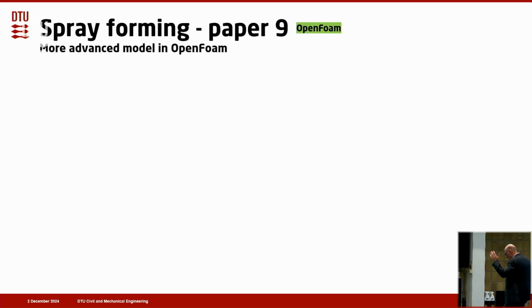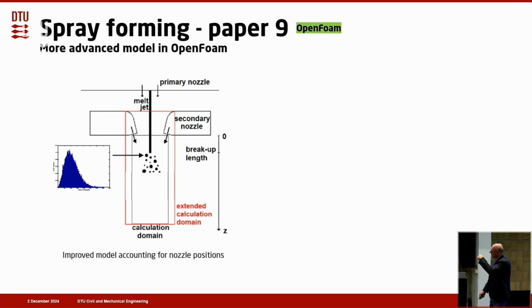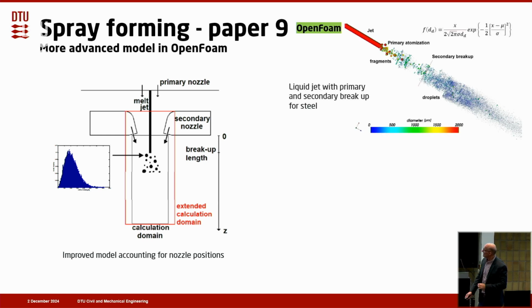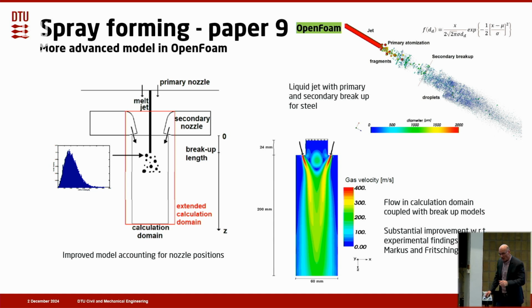Then we finally, in spray forming, did a model in OpenFOAM, which was a more, you could say, advanced CFD program, where we looked at the calculation domain relatively close to the nozzle positions and looked at both primary and secondary breakup. And then we could make a simulation like this, taking turbulence with a k-epsilon model into account. And then this was a substantial improvement as compared to the literature at the time.